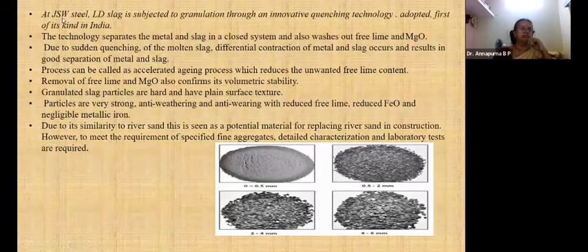So JSW, Jindal Steel Works, has developed another method of reducing this. The slag is subjected to granulation through an innovative quenching technology. This technology separates the metal and slag in a closed system and also washes out free lime and magnesium oxide. Quenching is sudden cooling of the molten slag. Differential contraction of metal and slag occurs and results in good separation, because both have different contraction capacity. So metal and slag can be differentiated. The process can also be called an accelerated aging process, which reduces the unwanted free lime content. Removal of free lime and magnesium oxide also confirms its volumetric stability.